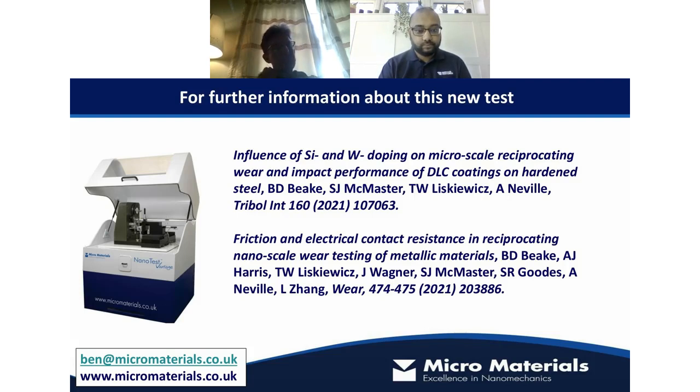I should say, it depends a little bit on mechanism. If the crack is occurring from tensile stresses at the back of the probe, then that potentially is seen on the surface as well. So there you would have access to that just through the scratch data, just through the SEM as well.